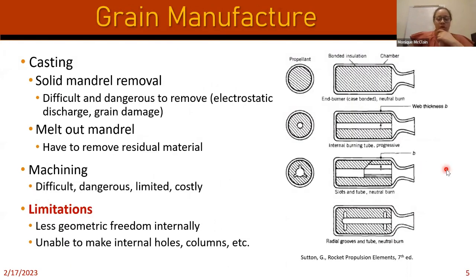So how do we make those initial geometries? Typically we cast a material within a mold. This wouldn't necessarily be a mold because we have a nozzle at the end, but imagine the nozzle is cut off here, and essentially we have a few options of what we can make. We could pour our slurry into basically a cylinder, and potentially just have the whole thing filled up. If we ignited the motor so it burns from this end outward, we would have a constant burning surface area. As the propellant regresses, that burning surface area is going to be the same because it's just a circular cross section the whole way. So this will give us a particular type of thrust profile.